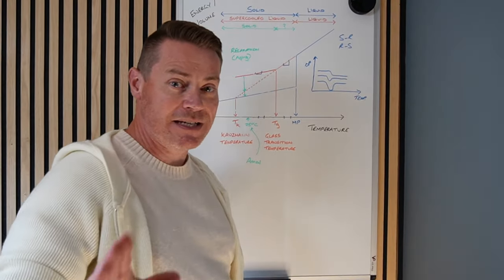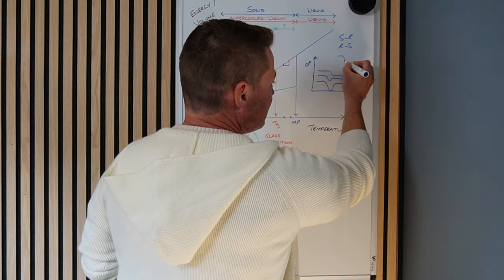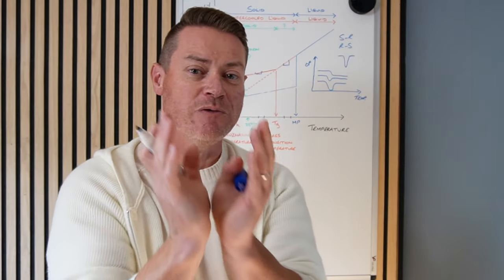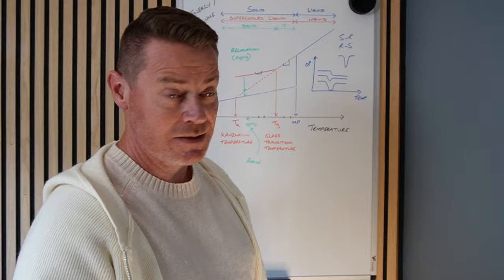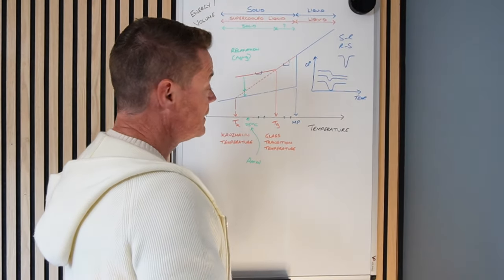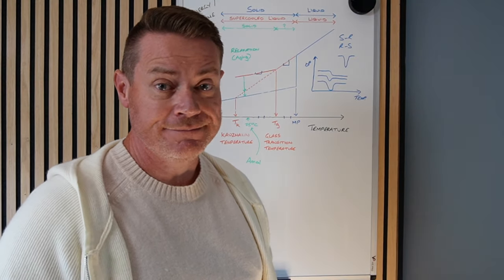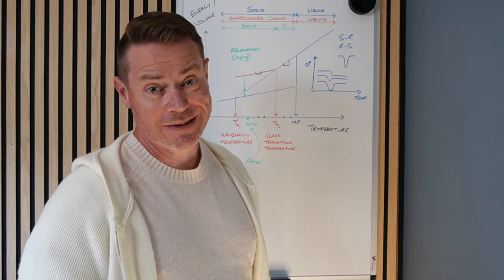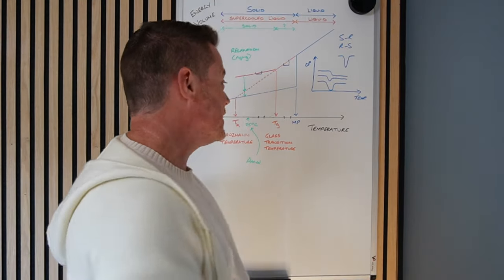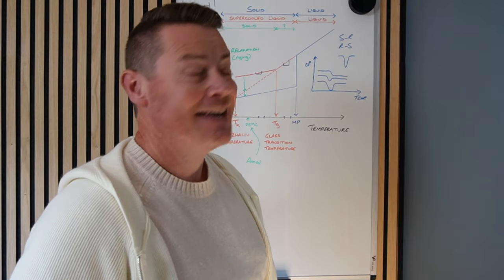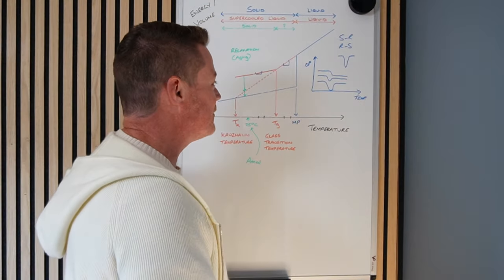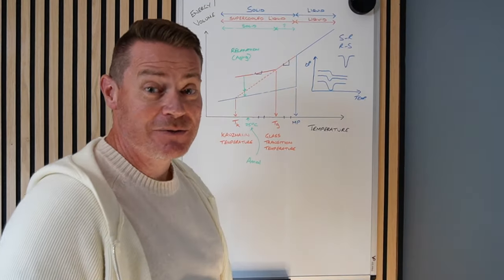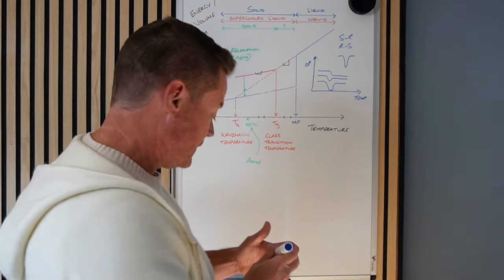I need to be clear: your material may have crystallized on storage. But if it has crystallized, the melting endotherm in a DSC is always sharp and narrow, because materials melt over a narrow range. If you start to get endotherms which are broadening out, it can indicate the material is impure and crystalline, but it can also be because your material was amorphous and is not melting — as we covered in the video entitled 'Why Amorphous Materials Don't Melt.'